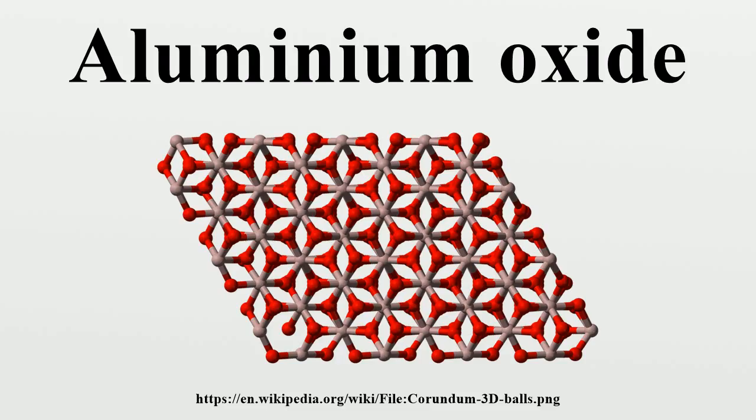Structure. The most common form of crystalline aluminium oxide is known as corundum, which is the thermodynamically stable form. The oxygen ions nearly form a hexagonal close-packed structure with aluminium ions filling two-thirds of the octahedral interstices. Each Al3+ center is octahedral. In terms of its crystallography, corundum adopts a trigonal Bravais lattice with a space group of R3c. The primitive cell contains two formula units of aluminium oxide.